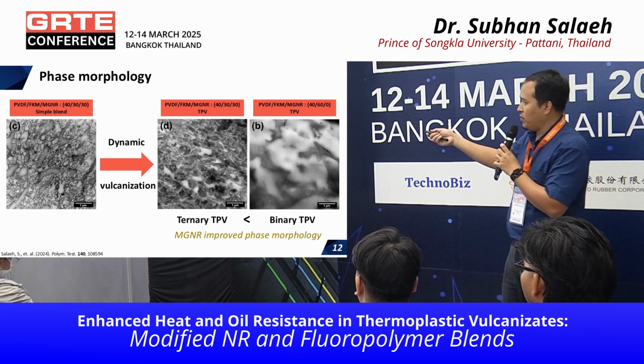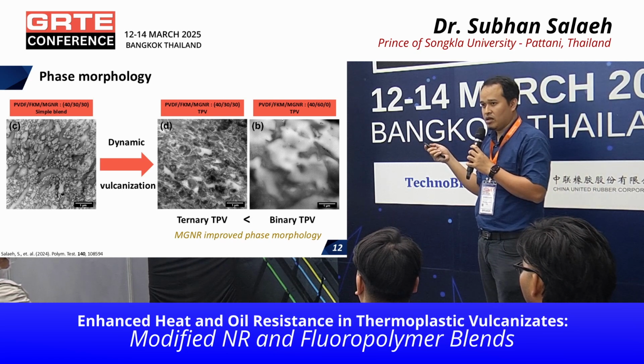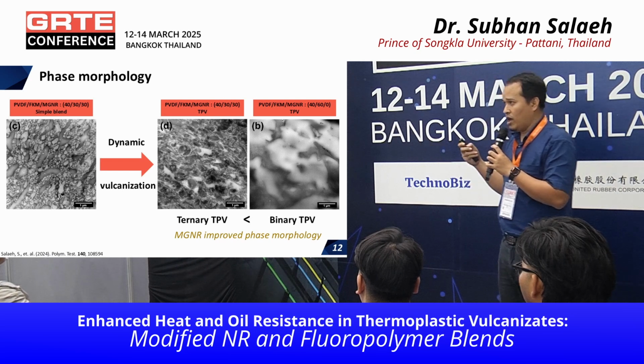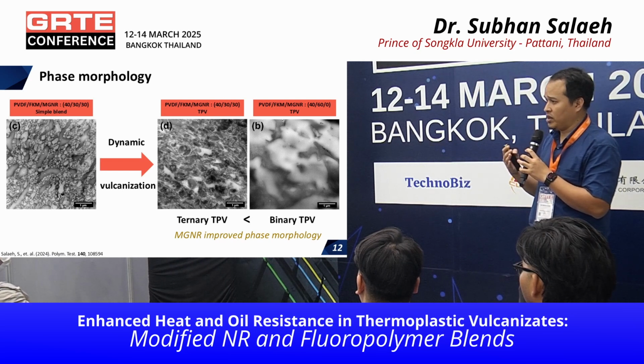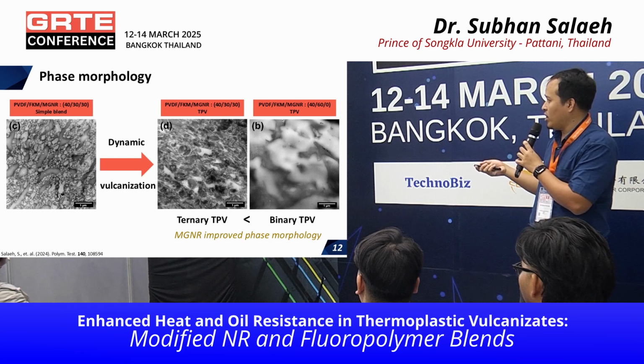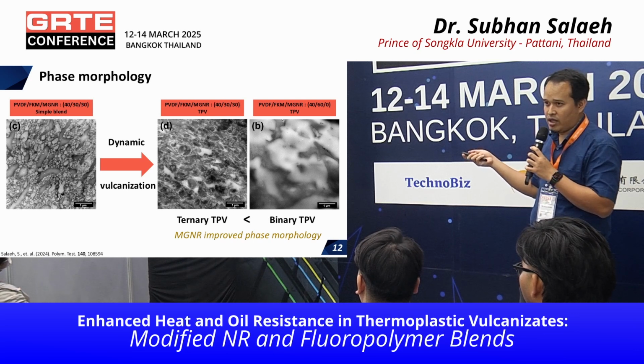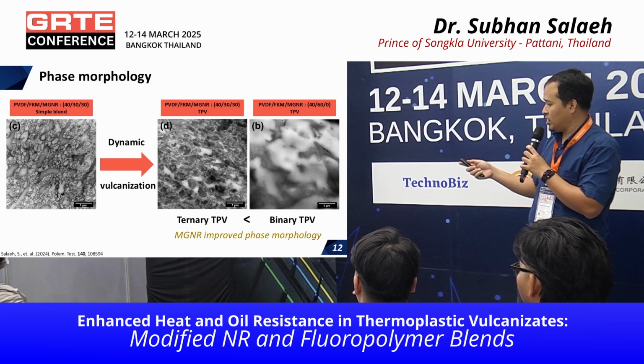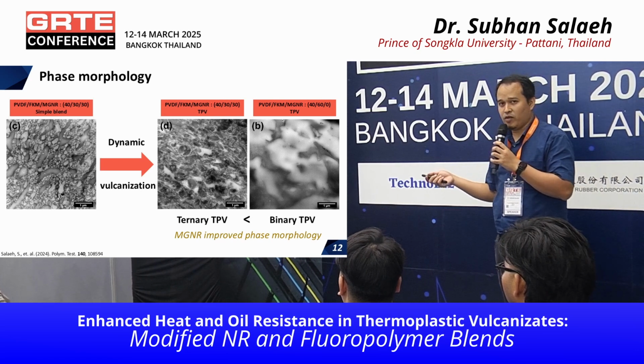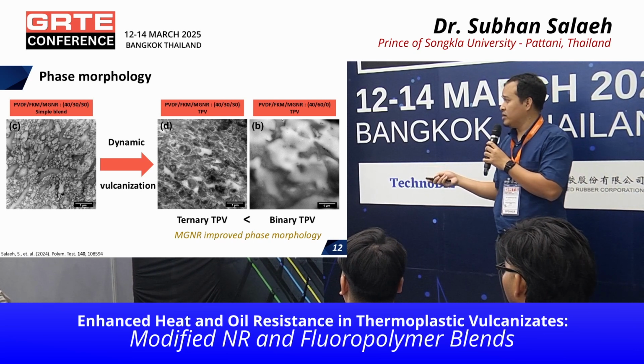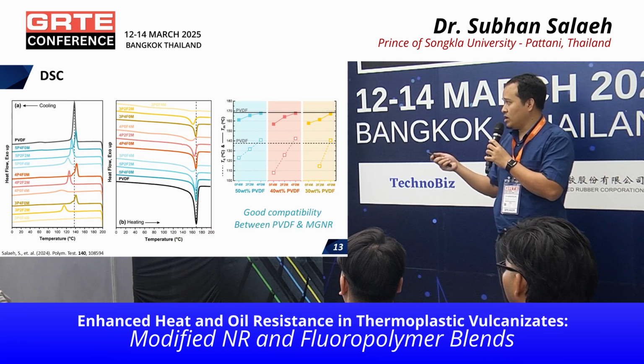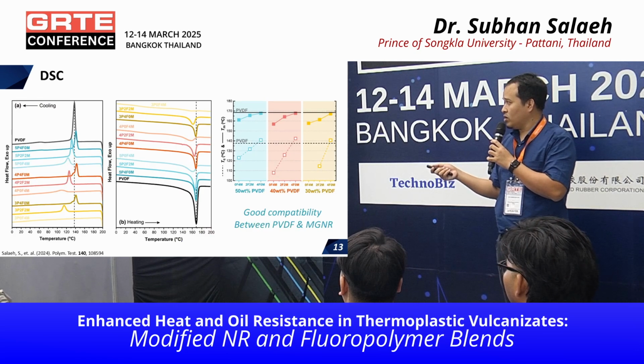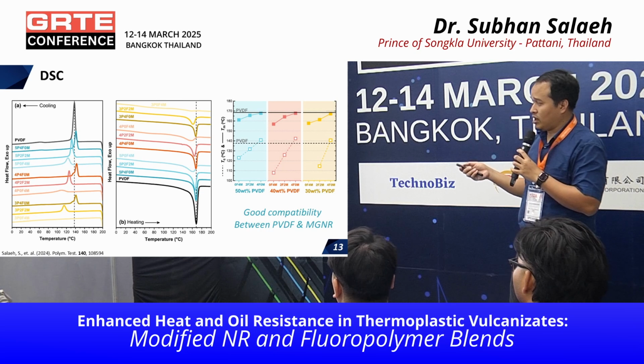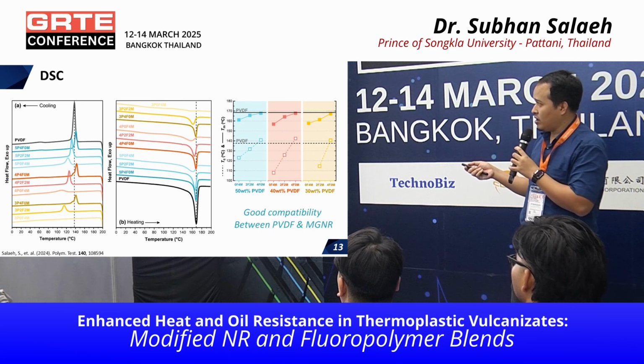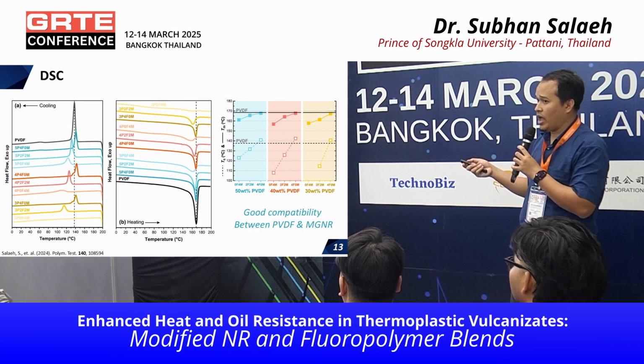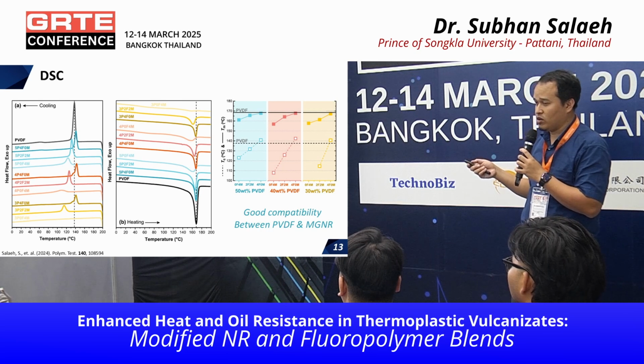And this is only PVDF and FKM. It shows large morphology due to viscosity mismatch between PVDF and FKM. That's why it shows large morphology and low mechanical properties. And we can see that the ternary blend shows finer morphology as compared to the binary blend. And also this DSC shows the lower crystallinity and melting temperature due to the addition of MGNR into the TPV.